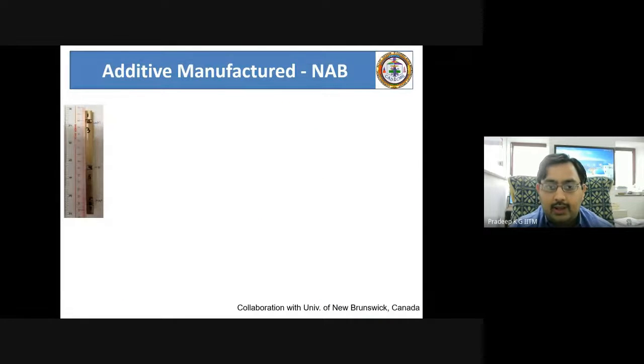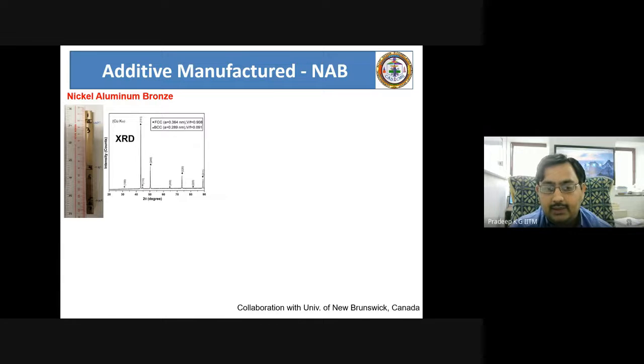So this is an example of an additive manufactured material, a nickel aluminum bronze. We wanted to compare 3 different regions for their microstructural phase evolution. So this is an XRD plot of one of these layers, which says it is a face-centered cubic structure, but we have some body-centered cubic structure precipitates sitting inside.